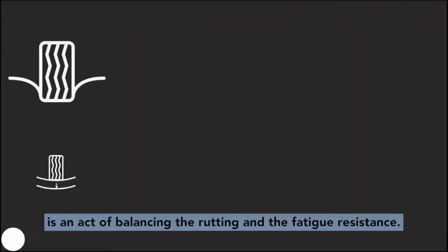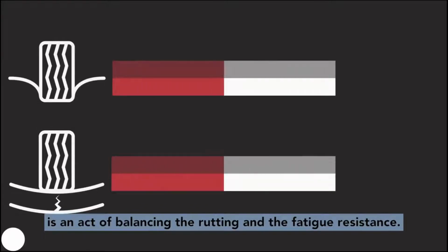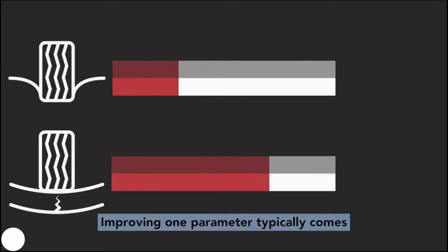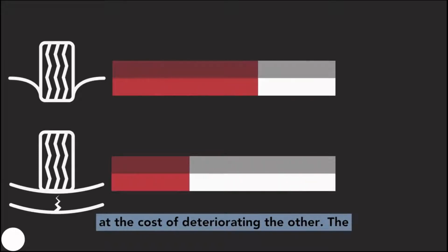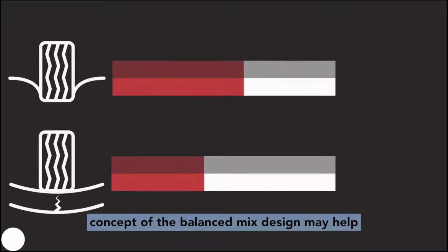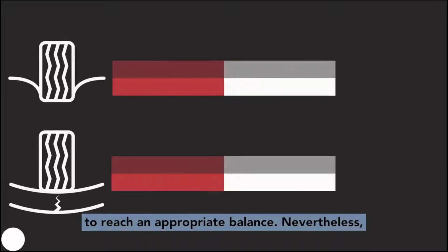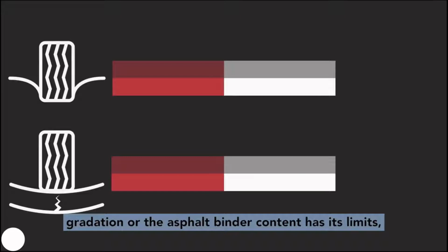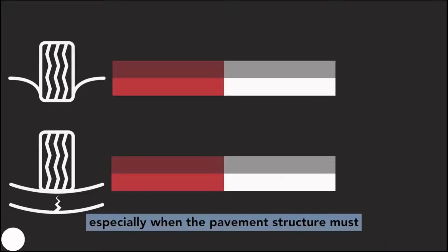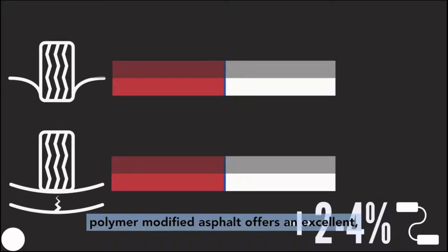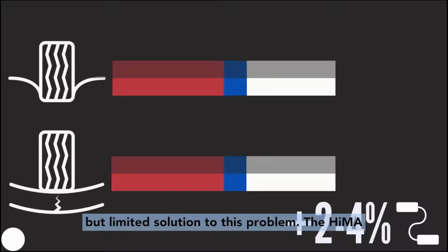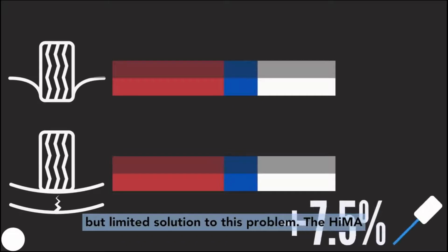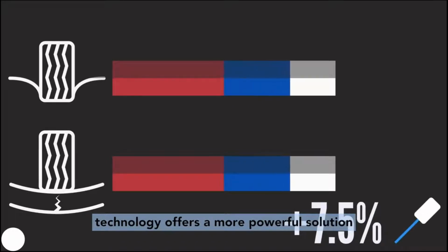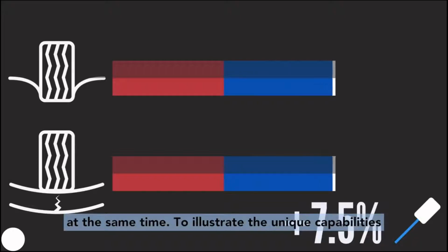Asphalt mixture design is an act of balancing the rutting and the fatigue resistance. Improving one parameter typically comes at the cost of deteriorating the other. The concept of the balance mix design may help to reach an appropriate balance. Nevertheless, making incremental adjustments to the aggregate gradation or the asphalt binder content has its limits, especially when the pavement structure must be thin or is subject to a heavy traffic. Conventional polymer modified asphalt offers an excellent but limited solution to this problem. The HiMA technology offers a more powerful solution to easily address both fundamental distresses at the same time.